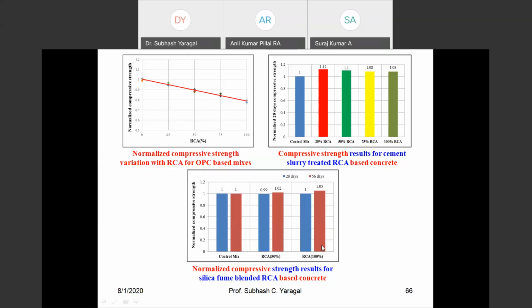So in this case, we have done the strength results for silica fume blended. Part of the treatment is by silica fume. There also we are able to get good strength. Again, a very small amount of silica solution is used for treating this recycled coarse aggregate.